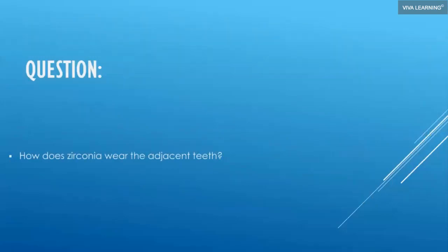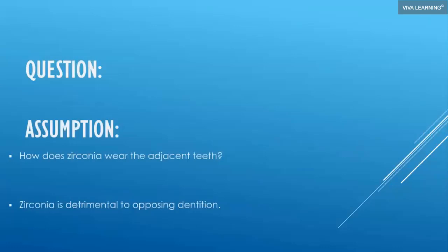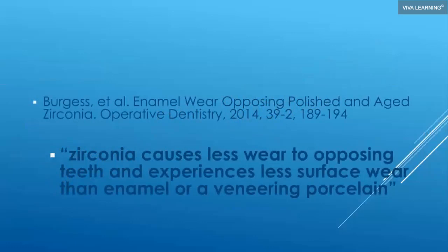Well, people say to me, well, zirconia is so strong, it's so hard. How does it wear the adjacent teeth or the opposing teeth? Well, I guess it really depends on what you do with that zirconia. The assumption is zirconia is detrimental to the opposing dentition. The reality is that's really a myth, because Burgess found that zirconia caused less wear to the opposing teeth and the other teeth experienced less surface wear than enamel or veneering porcelain.